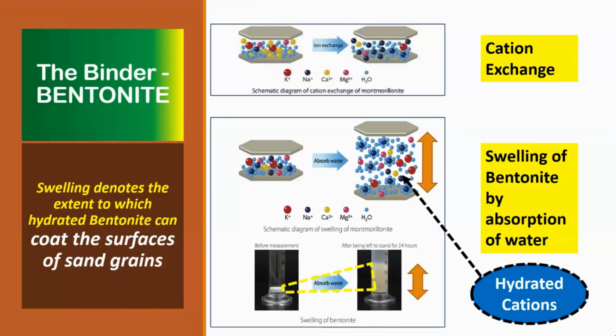You know, when you make the mold, it is not the sand that is going to hold together. It's only the binder that is going to hold together. So the binder has to be entirely on the sand, and then it is a binder to binder contact between the two sand grains that is going to determine how the sand grains are going to be held together, and then they are going to make the mold.